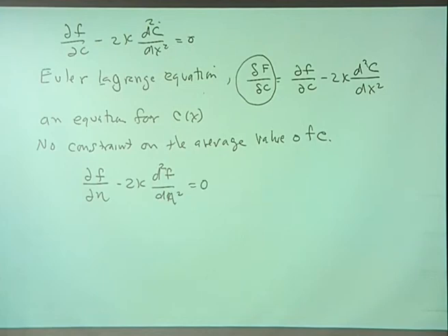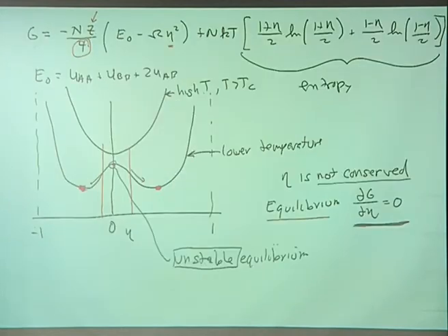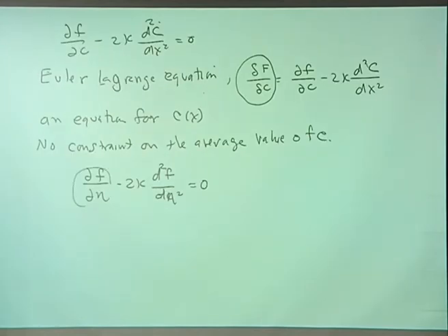And you'd be free to change the value of the order parameter any way you'd like to make that equal to 0. For example, in the system I just gave you, the equilibrium would be down here at the bottoms. You look at this equation, and the way to get equilibrium would be to say that's equal to 0. In other words, the order parameter is uniform at equilibrium.